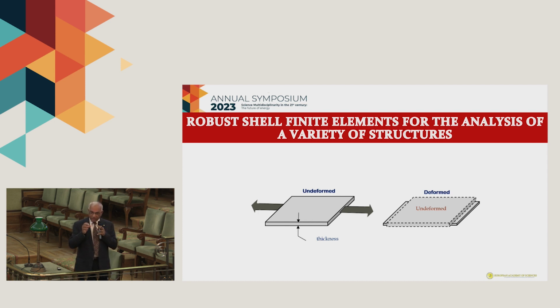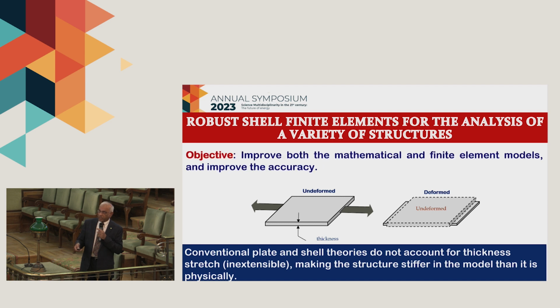After a while, you see, instead of dark blue, suppose the balloon was a blue balloon, it starts becoming a little bit faint color, light blue, because the thickness of the balloon is getting thinner in order to accommodate the large area, right? So that is what happens to the structures. So if you subject them to very large loads, the material has to flow from the thickness into the in-surface. And this is not accounted for in the existing models. And that is where we made a change and developed a finite element model so that you can study a variety of structures that I showed you on the previous slide.